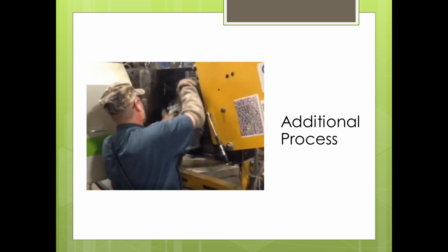We do utilize some additional processes to continue to refine the thermoplastic after it's settled out and floated on top of the water and been removed and dried. The most difficult contaminants to remove out of the process are actually other thermoplastics, because they are also lighter than water in their weight. Polypropylene, for instance, is about 0.90 grams per cubic centimeter, and high density polyethylene is about 0.95 on average for density.